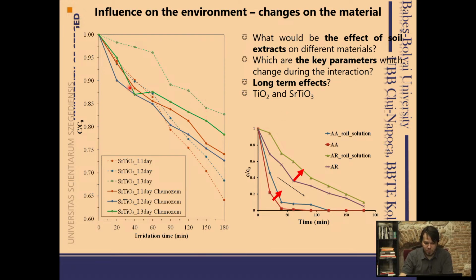Let's say if this was the starting material, the dotted lines are for the particles which are in nature. So they were not inactivated at all. In some cases, we even registered an increase in semiconductive properties, not just a decrease. And in other cases, of course, we also didn't observe any decrease in the semiconductive properties. So these materials are active in nature, so not deactivated.